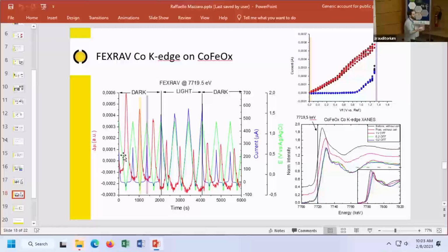Interestingly, the opposite trend was observed for the other catalyst I showed before. So this is a cobalt iron oxide. And in this case, again, we see these bumps. These are much higher in this case. It's also a different catalyst, so maybe a different amount of catalyst. This is a much larger peak. In this case, we also see some degradation in the first step of the experiment. But you can also see that upon illumination, these peaks are shrinking. So the potential window in this case is reduced in light conditions. So we have an opposite trend for the two catalysts.